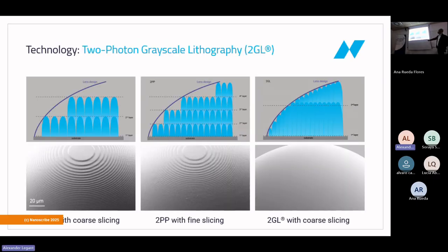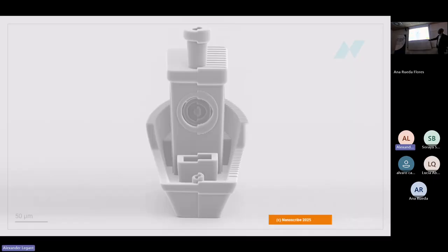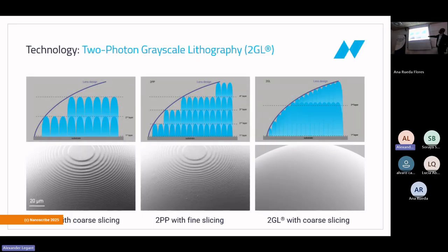The standard approach would be that you just expose one layer after the other, resulting in some staircasing, what you see over here. You don't want to have that, you want to have a smooth surface roughness. So you can reduce this staircasing effect by embedding more layers, by decreasing the slicing distance, what you see over here. But this goes hand in hand, of course, with increased printing time. The more layers you have, the more time you need.